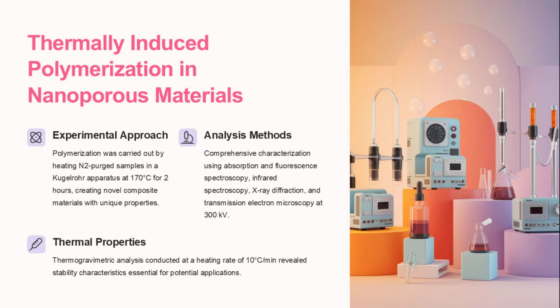The research focused on thermally induced polymerization within nanoporous materials, creating novel composite materials with unique properties. The experimental approach involved heating N2 purged samples in a Kugelrohr apparatus at 170 degrees Celsius for 2 hours to induce the polymerization. Comprehensive characterization techniques were used to analyze the materials, including absorption and fluorescence spectroscopy, infrared spectroscopy, X-ray diffraction, and high-resolution transmission electron microscopy.